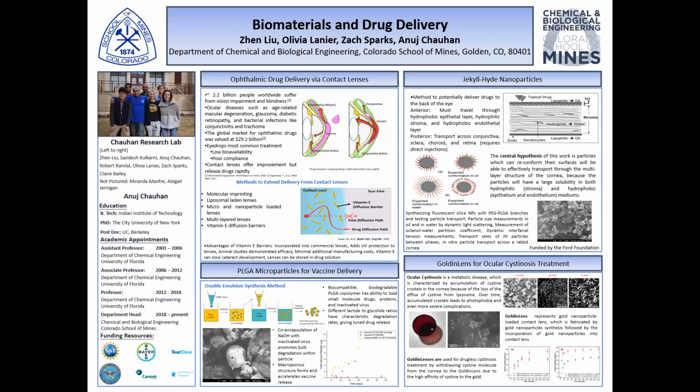In order to improve this, there are methods to extend the delivery of the drug from the contact lenses. Examples are molecular imprinting, liposomal-laden lenses, micro and nanoparticle loaded lenses, multi-layered lenses, and vitamin E diffusion barriers, all of which this lab has conducted work in the past and in the present. Vitamin E diffusion barriers is one of particular focus right now. With the incorporation of vitamin E, this eliminates the free diffusion path and gives the overall longer drug release.